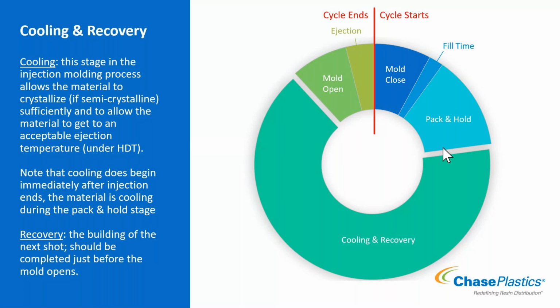So, if you need to pack for longer to account for sinks or voids, and say you needed to add 3 or 4 seconds to this pack and hold, you can effectively also take that off of the cooling and still have the same amount of technical cooling time. Just because the timer for cooling isn't running at that point, we know that as soon as we are pushed up against the mold wall in pack and hold, we have effectively started our cooling. So that's a little nuance to keep in mind.